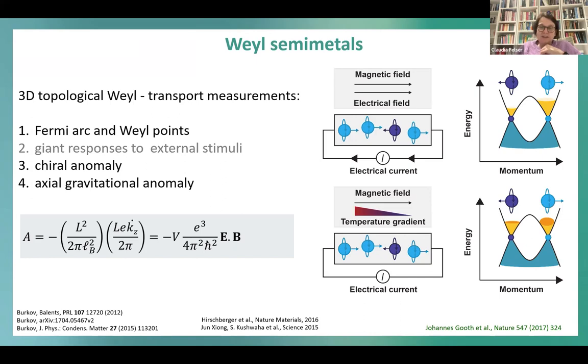This was a concept predicted by people like Burkov et al. So that they say you should see a negative magnetoresistance effect. And they gave also some prediction, from Harvard, what happens if you apply an additional temperature gradient. So this involves entropy, and you should see the axial gravitational. So this is like what you find in some papers, and every condensed matter physicist became very excited to find the right material and to do this measurement. And we did this for a material like niobium phosphide, you see on the next slide.